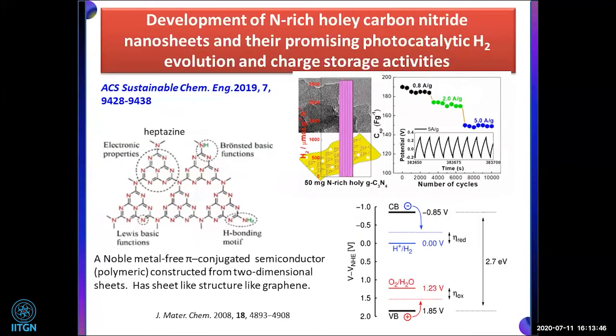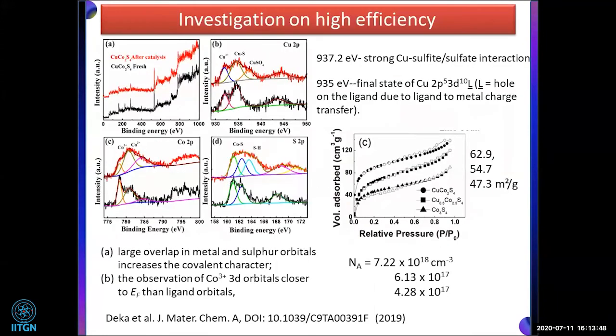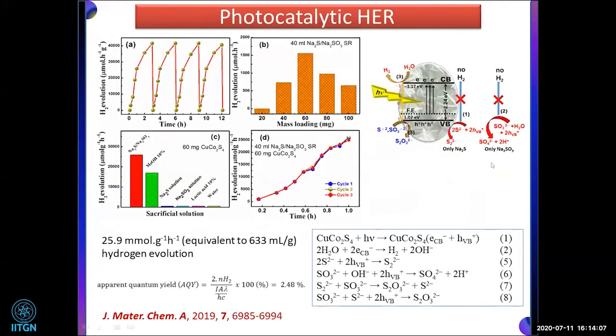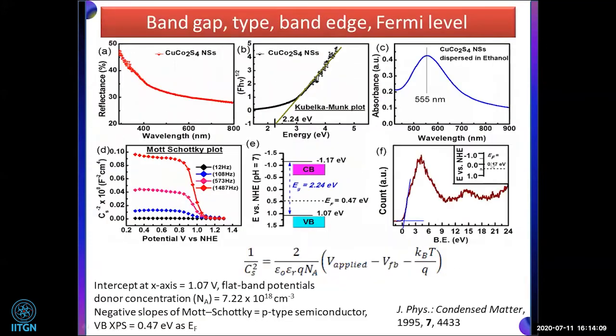And there is one more thing I must inform you, that we got from the XPS also: this cobalt 3d and sulfur 3p have very good overlap, and the large overlap in the metal-sulfur increases the covalent character. And that cobalt 3d is closer to the Fermi level of this semiconductor material.